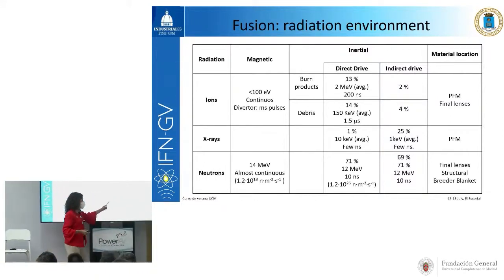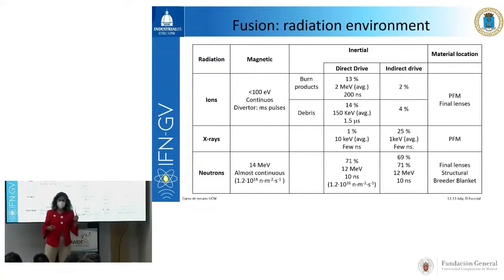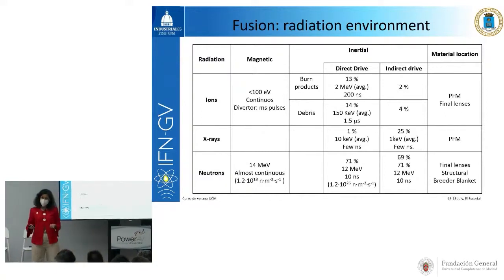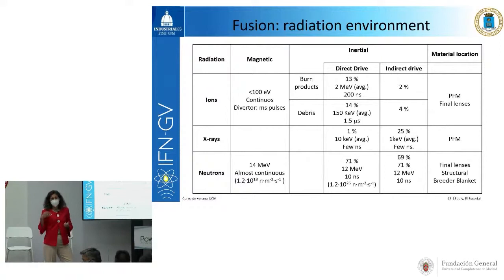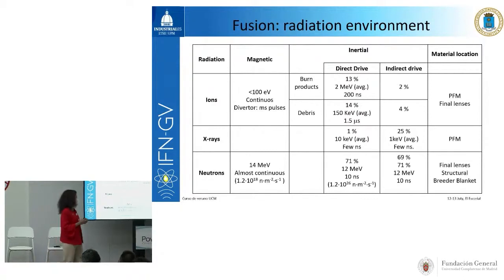And this X-ray is going to affect mainly the plasma facing material, and what they are going to do basically is hit the material. Well, the energy deposited by those X-ray in the material is so high that they can even melt the material, just considering nothing more than the energy deposited by radiation in the plasma facing material, okay?